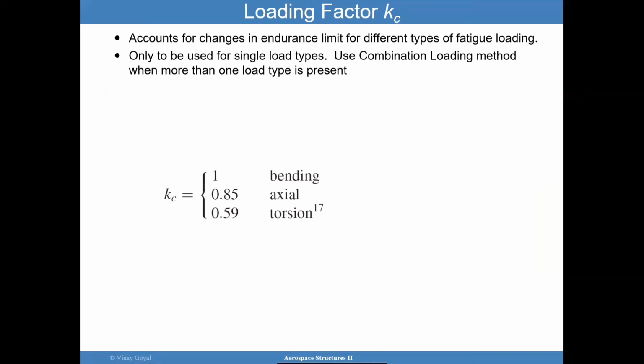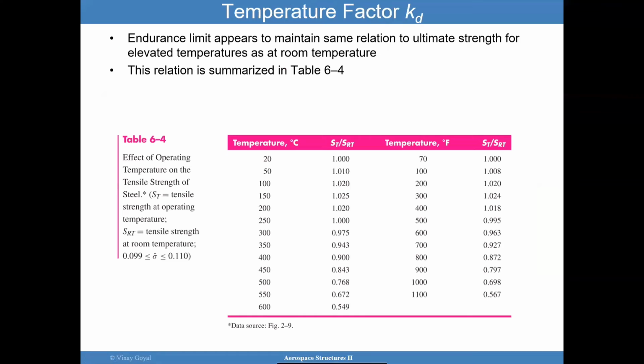The loading factor, if you had bending, the value is 1, for axial 0.85, and for torsion 0.59. So you have to correct it depending upon the situation that you have. The KD factor is a temperature factor, and this is specific to steel, but it may change for another material. The point is that as you go higher in temperature, you're going to affect the KD value significantly. So it's important to keep in mind in correcting your endurance limits.